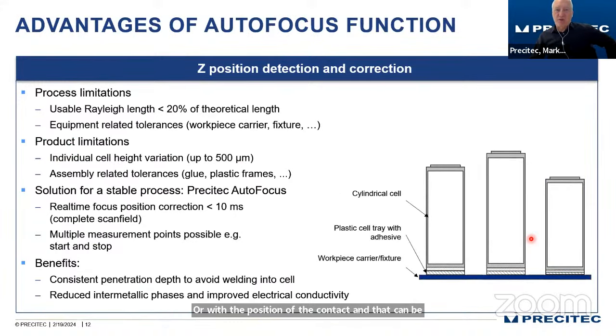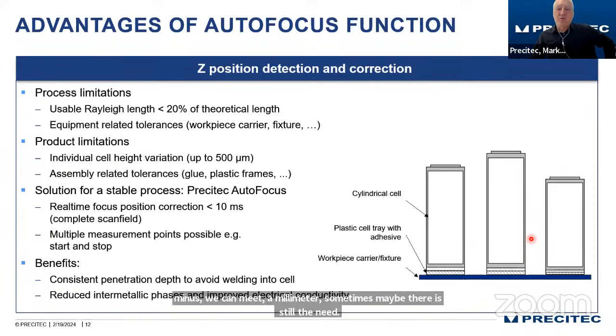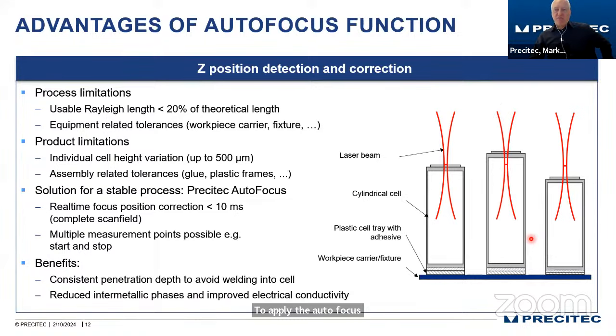So let's talk about the Z position. Even though the Canunda system is providing excellent Z-focus constants over plus or minus 3 millimeters, sometimes there is still the need to apply the autofocus. If you see something like that here with a poor Rayleigh length, for sure in these two situations you will not perform an excellent weld, and that weld will not really match the customer specifications.